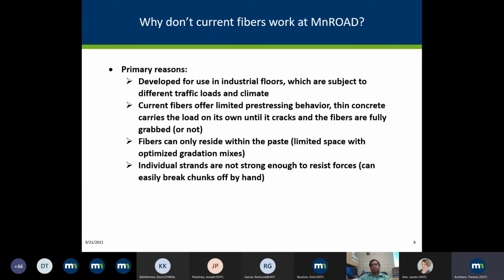So the question is, why don't current fibers work at MnROAD? When I say don't work, meaning that I'd like to see more capacity out of them, especially with the joints. Some of the reasons are that the fibers that we've been using were really developed for industrial floors. And we have different loadings, we have climate to deal with. So it's kind of a tall order for a fiber that was not really designed for those criteria. Again, the current fibers do not have pre-stressing behavior. So the concrete itself has to carry the load until it cracks, and then the fibers are engaged.